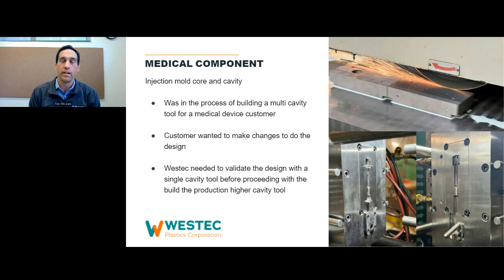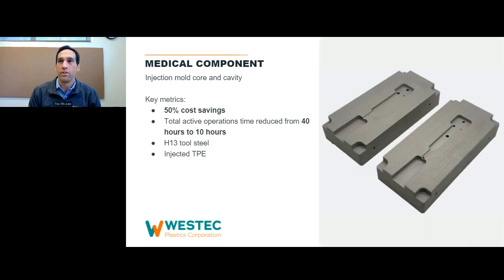And so very quickly, Westec was able to design the tool and print it using Mantle technology, perform a minor amount of finishing work as they dropped it into a mold frame, and then mold TPE samples that they were able to then share with the customer, validate the design, and then proceed with the larger program. There was a 50% cost savings here, and it took active operations time, toolmaker time, down from what would have been 40 hours to 10 hours. And this is again using our H13 tool steel.